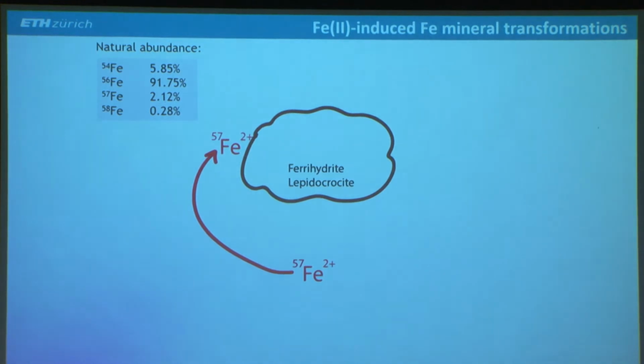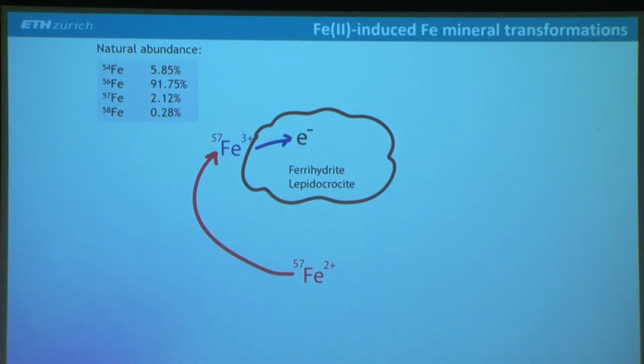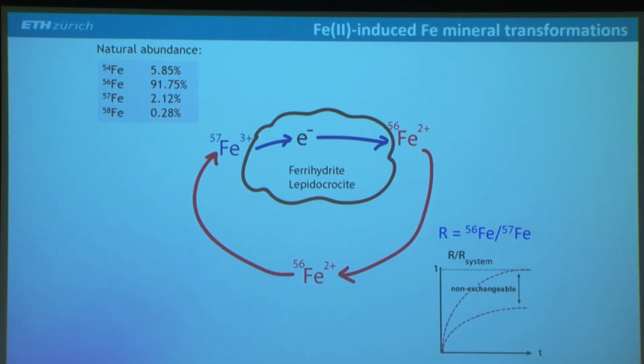And the iron could then get oxidized by releasing an electron, for example, into lepidocrocite or ferrihydrite. And this electron could reduce another iron atom somewhere else. And this will most likely be iron 56 because initially there's a 91% chance that this is iron 56. This can get released into solution, and so this can drive a recrystallization of the solid phases. This is well known for ferrihydrite. And so what we should then observe is a change in the isotopic ratio, so we can monitor the isotopic ratio in solution to get some handle on the kinetics of this process.